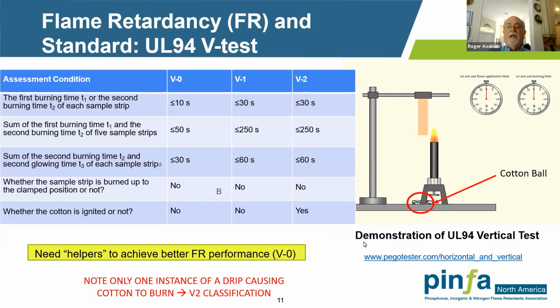The other very key thing, as you can see in this UL 94 test, is there's a wad of cotton. I've circled that in red at the bottom. What you don't want to have happen is that if the material does start to drip, that drip impinges onto the cotton and starts the cotton on fire. Now remember that typically this test utilizes 5 specimens, and then you have 2 instances of bringing the burner to the specimen. So you basically have 10 opportunities for a potential drip, and particularly a potential drip causing the cotton to burn. No matter what the extinguishing time is, obviously you want the extinguishing time to be as low as possible.